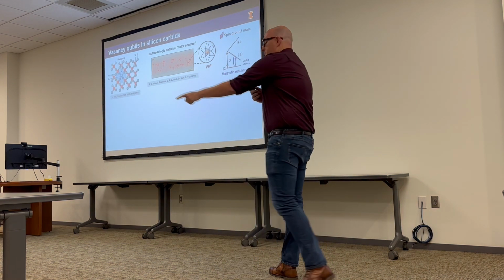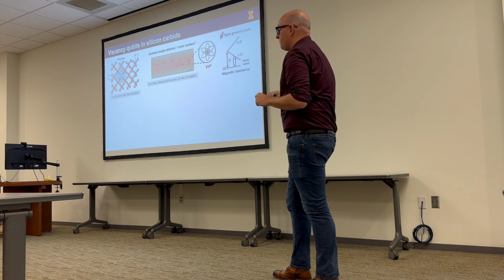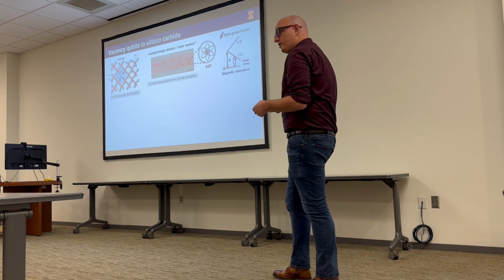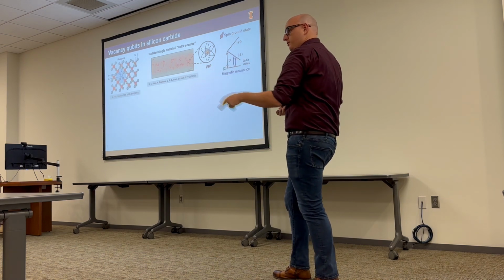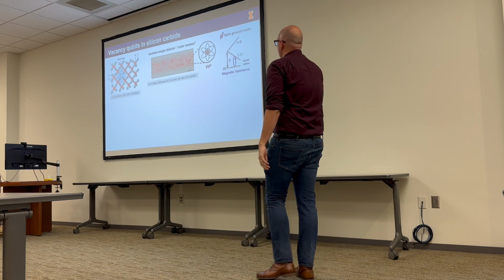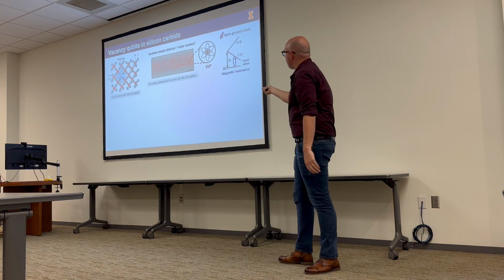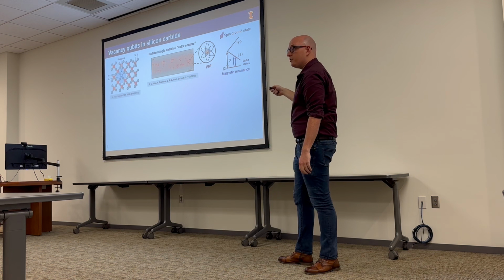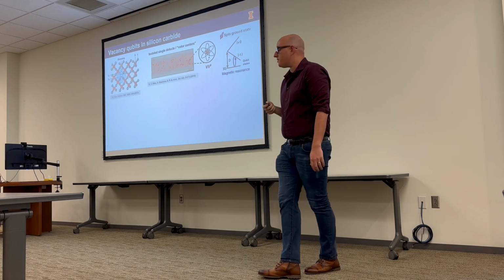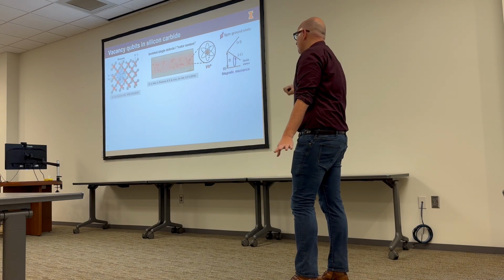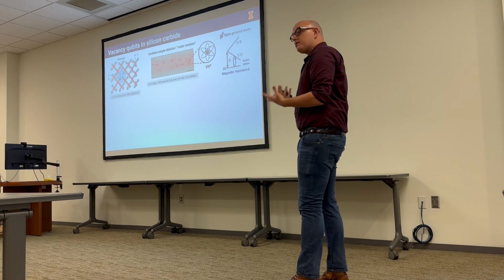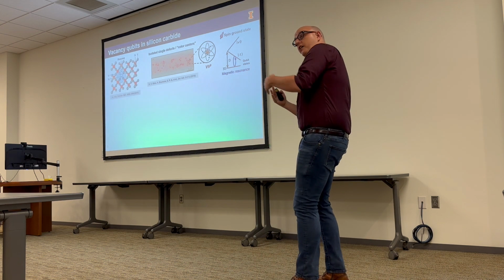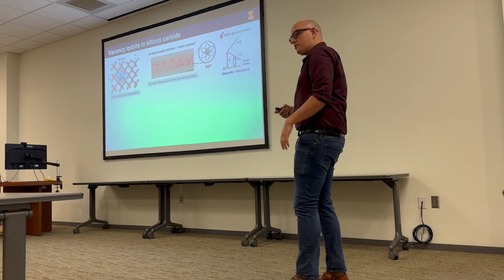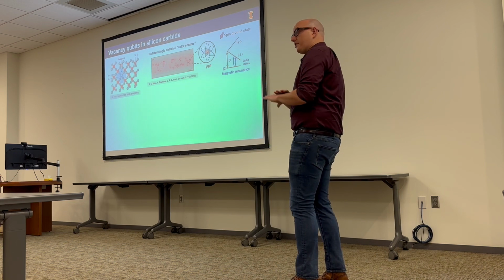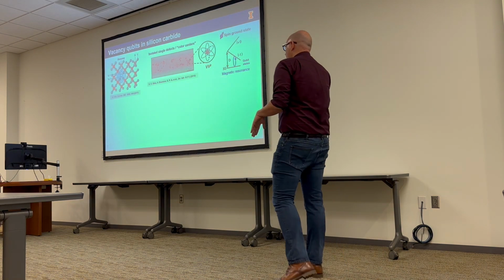Thanks. So partly to answer your question, in this divacancy, the ground state is a spin triplet. So there's not one unpaired electron, there's actually two, just because of the structure of the system. They sort of pair up to make this triplet state. So we have an ms equals 0, a projection 0 magnetic state, and then we have this plus minus 1 state. That's totally fine. We just use two of them as our two-level system. Because it's a simple electron spin, we can apply DC fields to shift the energies around, and we can apply AC fields to do spin rotations. And this is the same physics that goes into an MRI machine or an ESR machine. So we can use magnetic resonance techniques to manipulate this single electron.